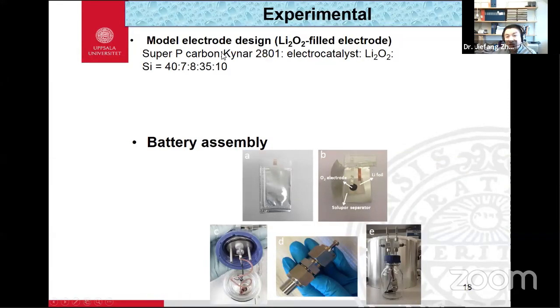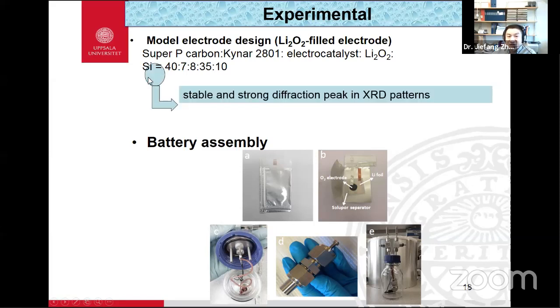So this is our cathode composition. As you see, we put in conductive carbon material, binder, and our electrocatalyst, and we also put in commercial lithium peroxide at the beginning, to mimic the battery stage at the end of discharge or at the beginning of charge. We also put in 10% silicon as the reference, because silicon is chemically and electrochemically stable, and it also provides a strong diffraction pattern.